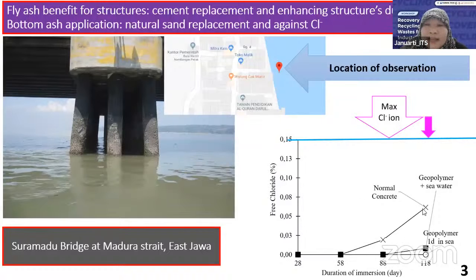When we put the normal concrete in immersion, in the sea water, for at least 4 months, chloride ion in normal concrete increased dramatically. And this point is just about 7.5 centimeters in the depth of the concrete. So it means that the free chloride ion can penetrate into the normal concrete, and it can initiate corrosions if we put a rebar or reinforcement inside the concrete.